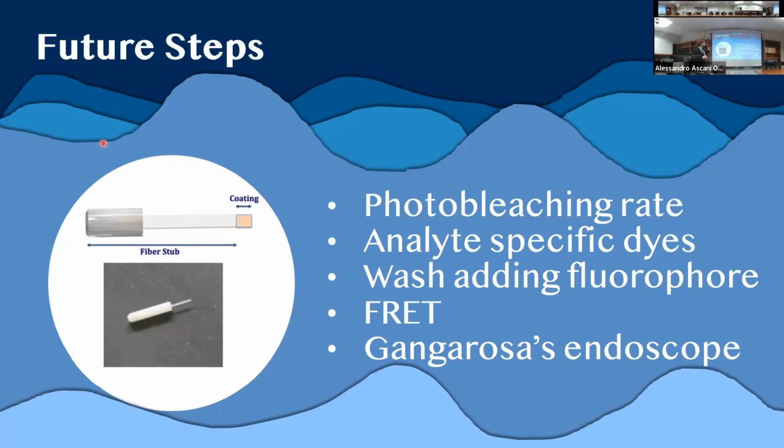We want to be able to use these sensors for long periods of time. So essentially, we want to decrease the photobleaching rate since it decreases the quality of our readings. And we want to study if these particles, by encapsulating and holding in the fluorophores, not only hold them in, but also limit this photobleaching rate, which is due to the too much excitation energy of the fluorophore.